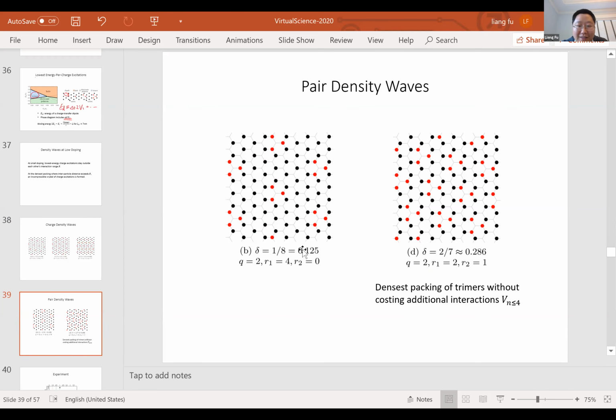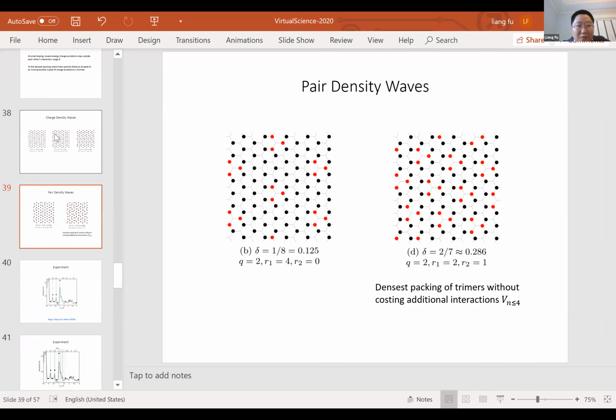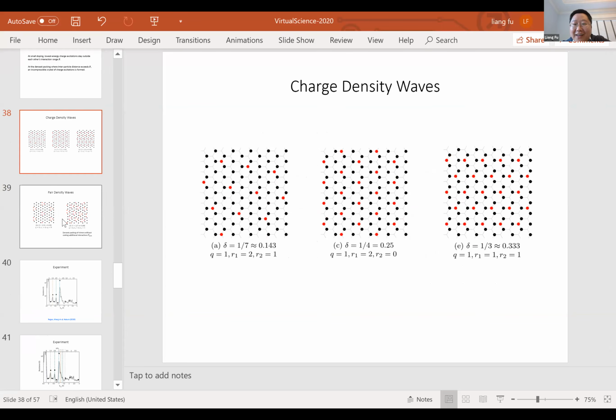And notice that they now occur at a different filling, right? At 1/8 filling, this is one example. And the closest packing of the trimers without costing any additional interaction up to the fourth neighbor is shown here. This occurs at 2/7 filling. So 2/7 and 1/3 are very close to each other, but they are different.